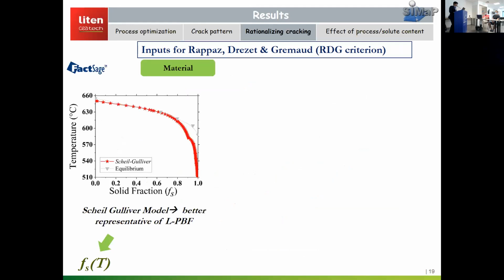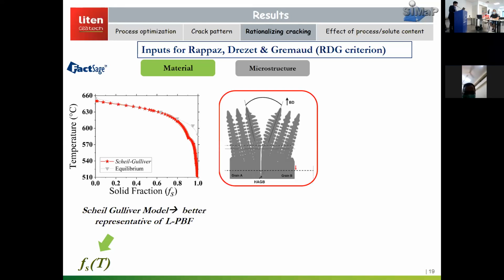So now, okay, we thought, let's use this model and try to identify the different inputs needed to run it. The first input is the material parameter, which is solid fraction as a function of temperature. We relied on the Scheil-Gulliver model to estimate this parameter. We thought this could be a better representative of the L-PBF process, since diffusion in the solid is neglected and there is infinite diffusion in the liquid. So compared to equilibrium, we chose Scheil-Gulliver to define the solid fraction as a function of temperature.